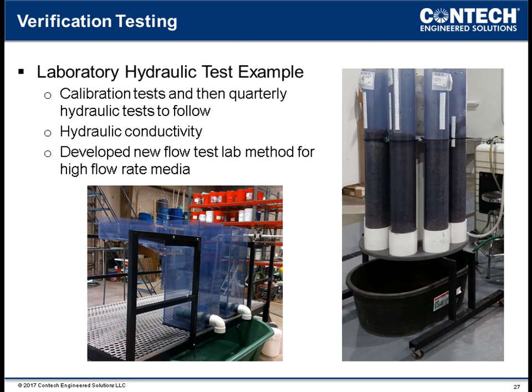There are standard methods for conducting permeability testing on slow flow media. However, a standard method doesn't exist for high flow rate bioretention media. Therefore, third-party consultation was sought to develop a suitable flow testing protocol that could be implemented in both the lab and the field. This test method was conservatively developed to test the media under both dry and saturated conditions, as well as to obtain 3 methods of hydraulic conductivity, including rising, constant, and falling head. Basically, research and development just ensures these flow rates are synonymous before moving forward with verifying a blend.